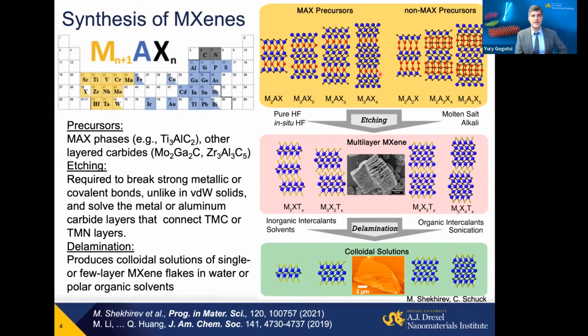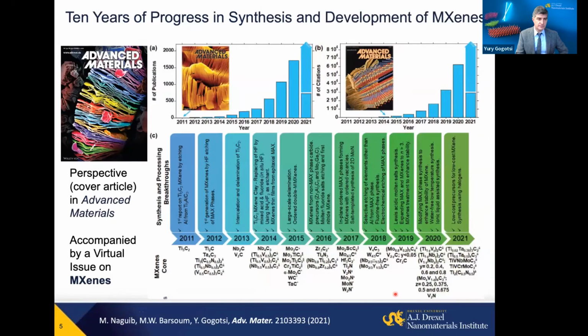So what we do, we etch them selectively, removing, say, a layer of aluminum, or one of the other elements marked here in blue. And we end up with layers of carbides and nitrides, now terminated by atoms coming from the environment. It can be oxygen, OH, chlorine, depending on what we use for etching, molten salts or aqueous salts. And now they look not like a ceramic, but more like thermally expanded graphite. Then the weak bonds between those layers can be easily broken by intercalation and sonication, forming single-layer flakes of MXene.